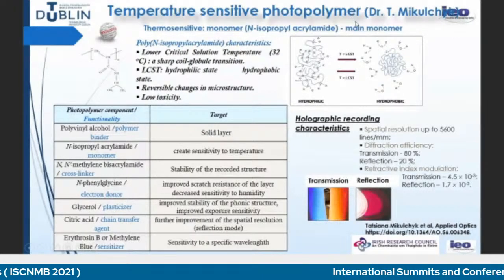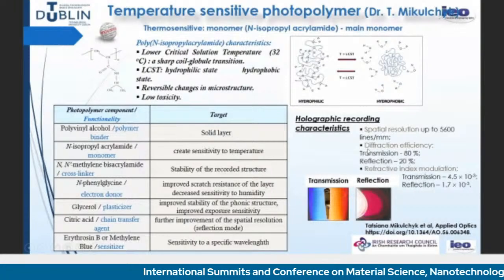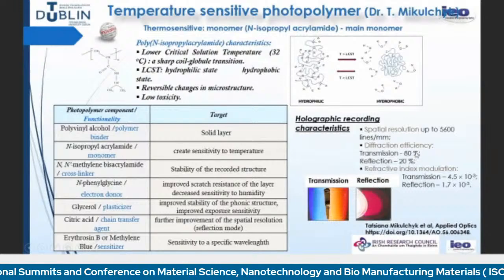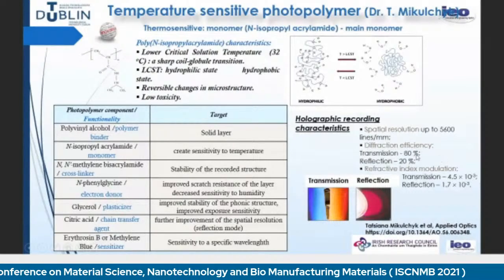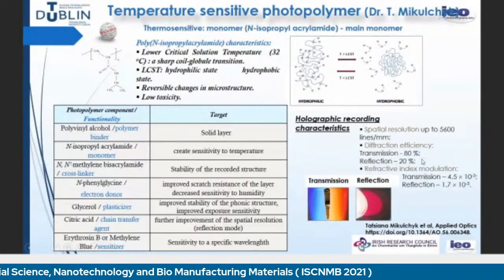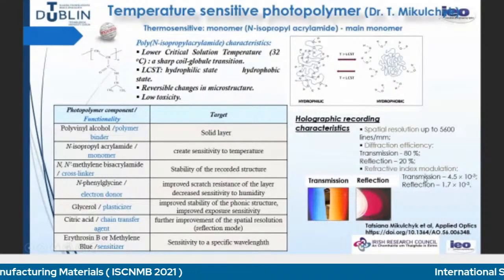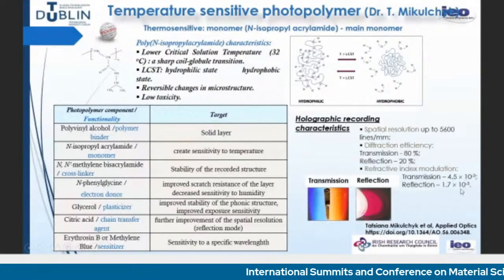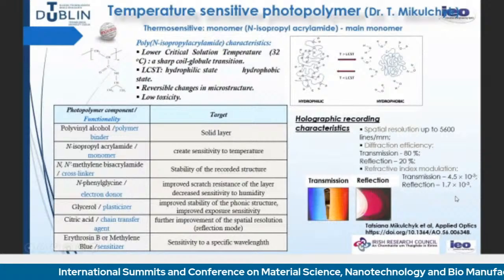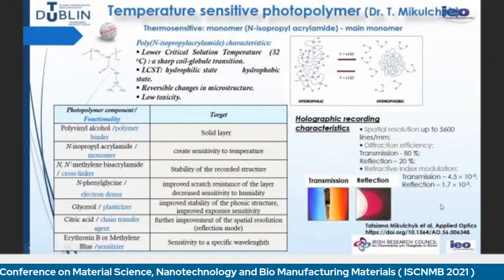And Dr. Mikulcik, one of my PhD students, developed this material for holographic recording. She has achieved very high diffraction efficiencies in transmission, actually repeatably 80%, but no theoretical limitation, and it can be even higher. In transmission, she gets 4.5 times 10 to the minus 3, which is a very decent refractive index modulation. And in reflection, where photopolymers typically don't perform so well, it is close to 2 times 10 to the minus 3.